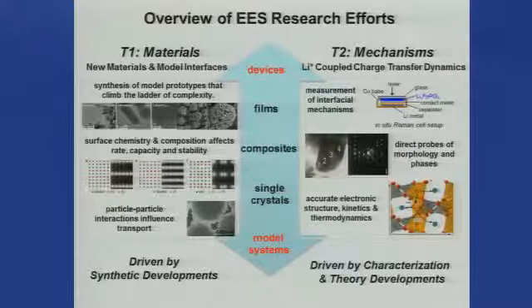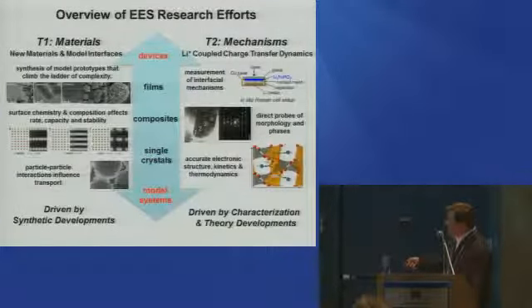But we also want to couple that to understand the mechanism of how these different aspects govern the Li+ coupled charge transfer dynamics. And so we've invented things like in situ Raman, where we can actually put this in a coin cell environment and cycle it like a regular cathode or anode material. And then we typically can couple that to high-resolution theory with Graeme Henkelman at UT Austin and understand what would be the actual electronic structure, what would be the actual structural dynamics that could occur as lithium diffuses in and across these types of complex architectures.